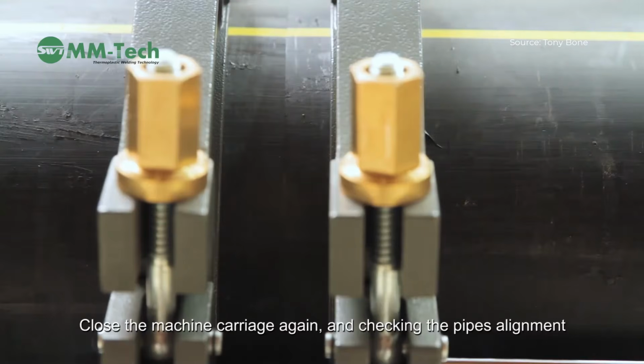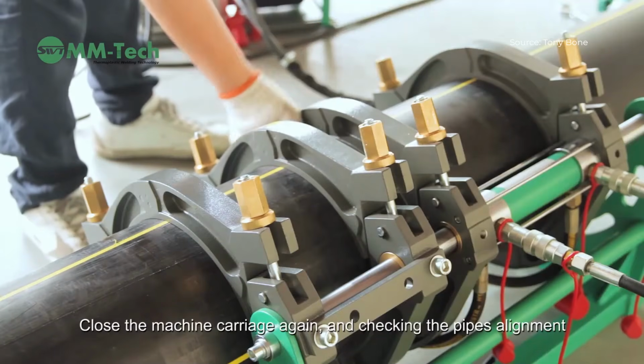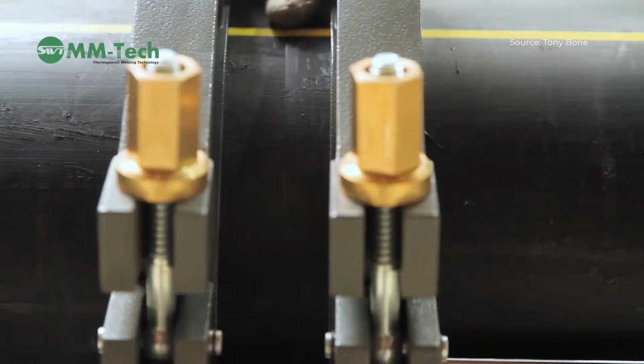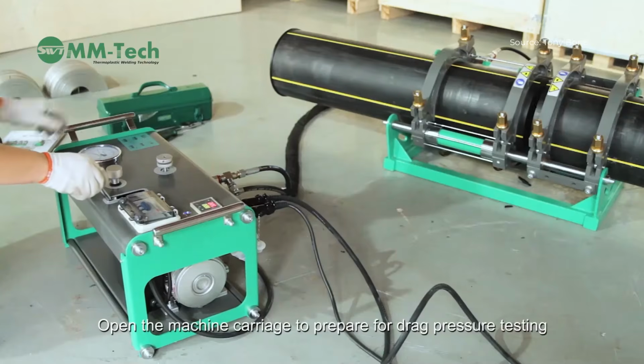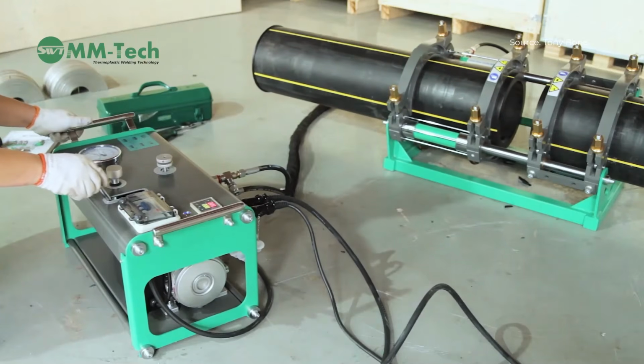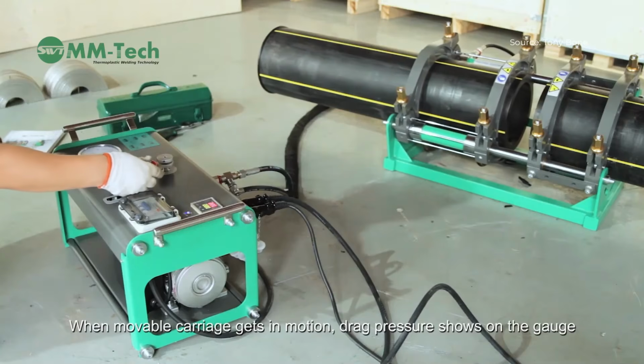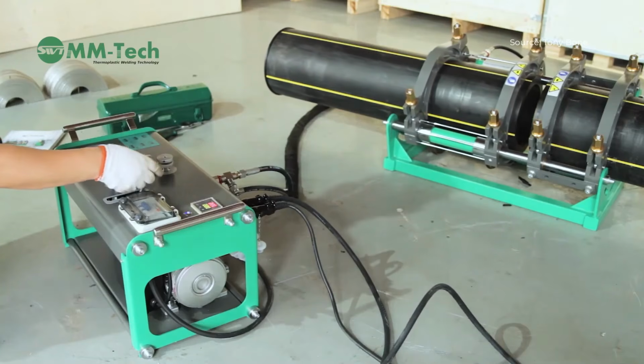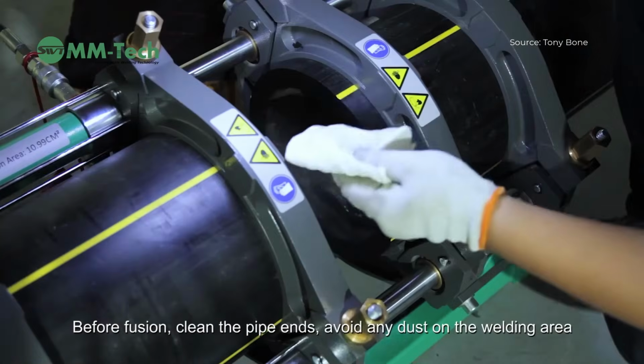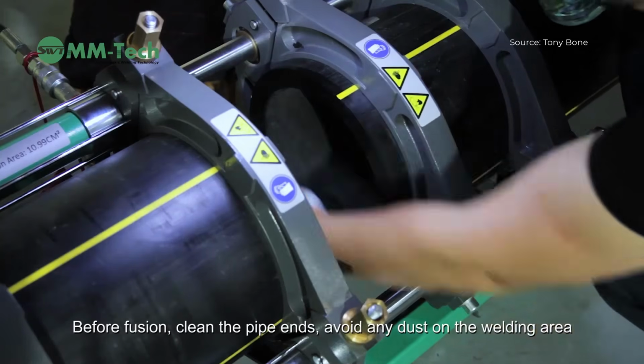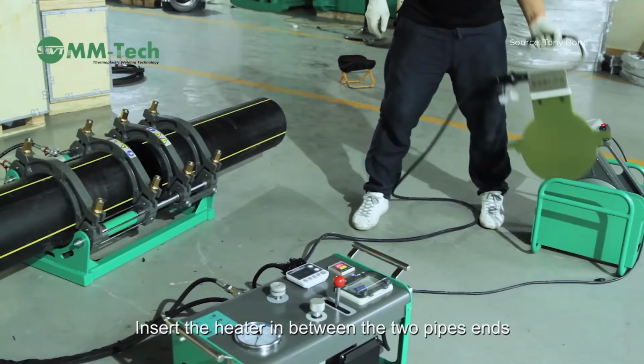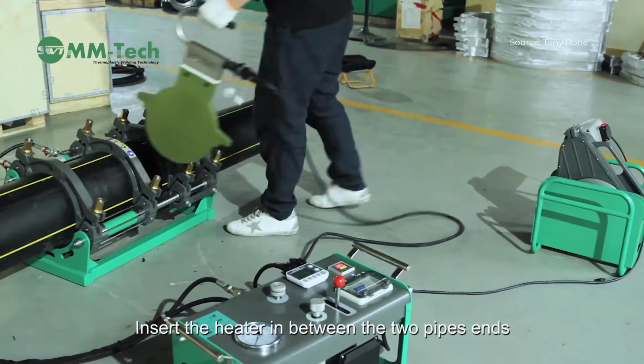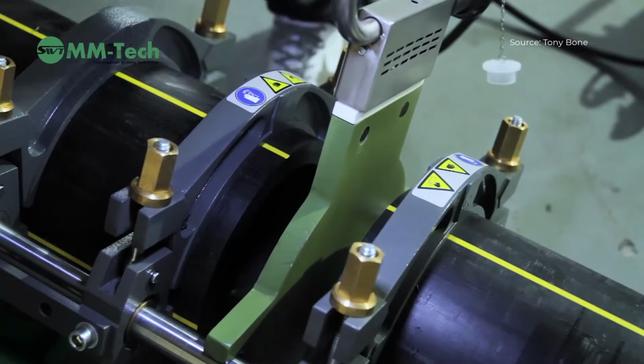Insert the heater plate between the pipe ends and close the carriage to allow soaking. When the soaking time T2 ends, open the pressure relief valve, open the carriage, and quickly remove the heater. Immediately close the relief valve and push the direction lever to raise pressure to the welding pressure P5 set point. Hold this pressure for about 10 seconds, then slowly release the lever.